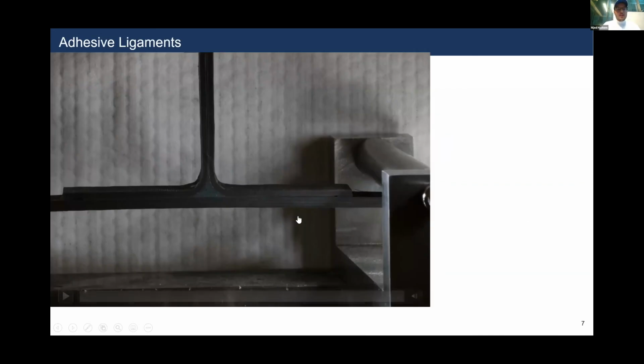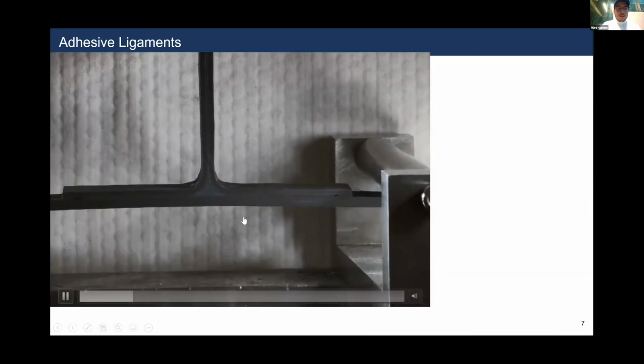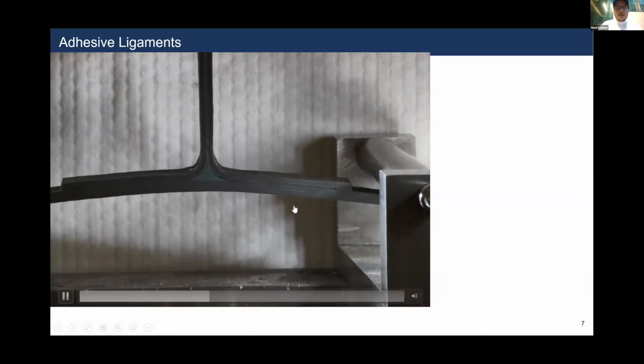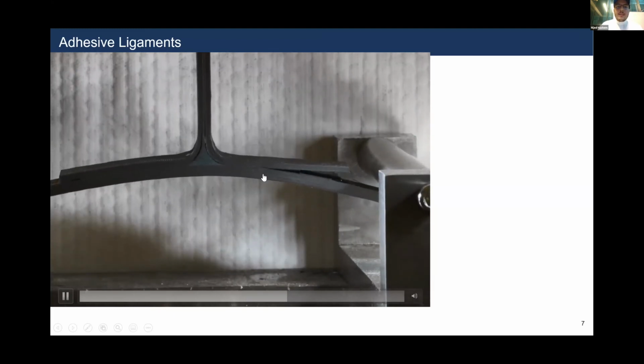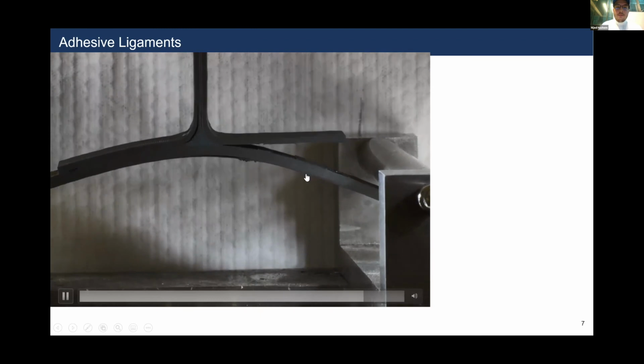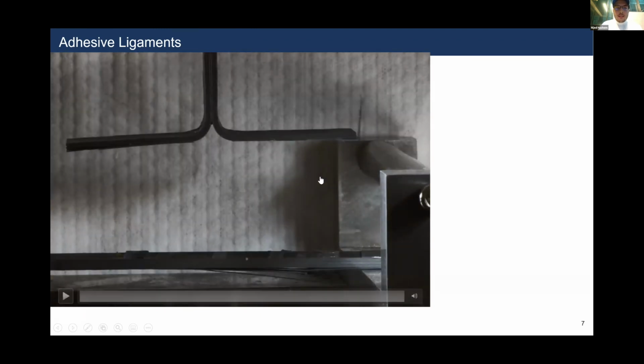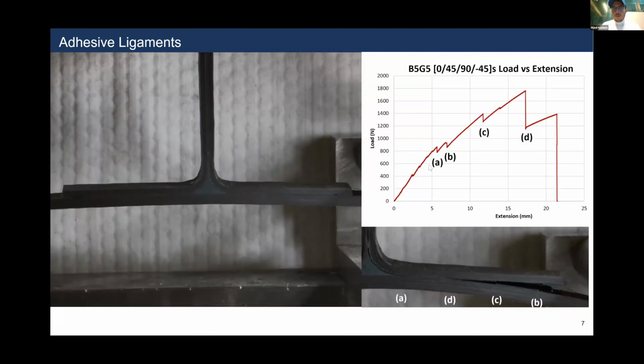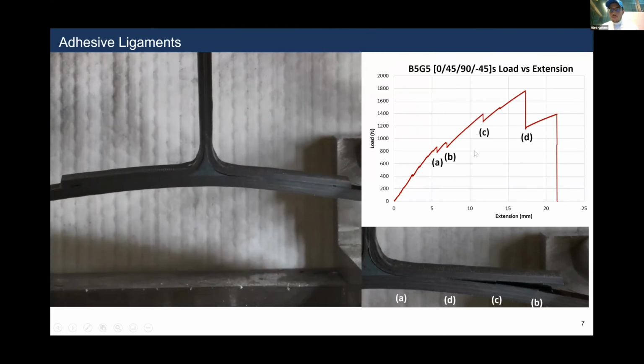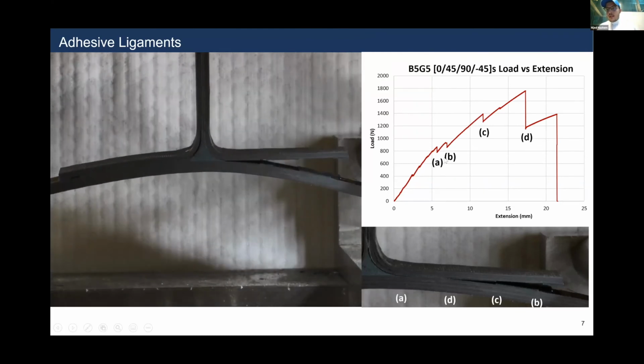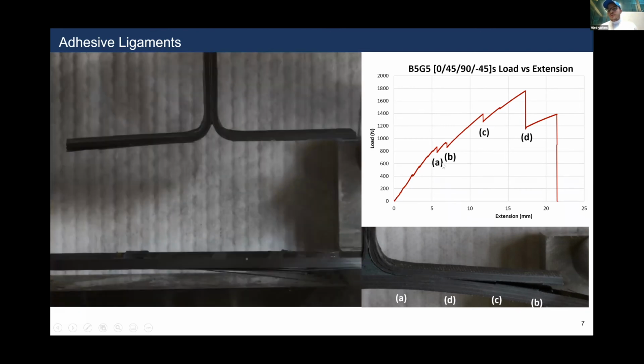And this is the reason: we took a video of the T-joint during failure, and we noticed that actually progressive failure happened where the crack started migrating up and down across the adhesive. And this resulted in the creation of what is known as adhesive ligaments, which Ran will talk about later in his presentation. But these adhesive ligaments actually were reasons for the improved toughness in the T-joint structures.